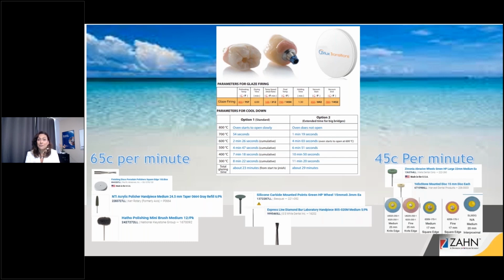So highly recommend polishing anywhere that you've ground on the zirconia. Some polishing wheels, you can get them in different shapes. If I can avoid using a stone at all, I will. I'll refine my margins, adjust my contacts and occlusion with more of a square edge rubber wheel, an aggressive rubber wheel. That way I'm killing two birds with one stone there. I'm doing my adjustments and I'm smoothing all at once. And you can also get the rubber wheels in a knife edge or a very thin rubber wheel that you can get into the embrasures with. And again, I'm stressing, please use a rubber wheel to open up your embrasures and not a diamond disc.